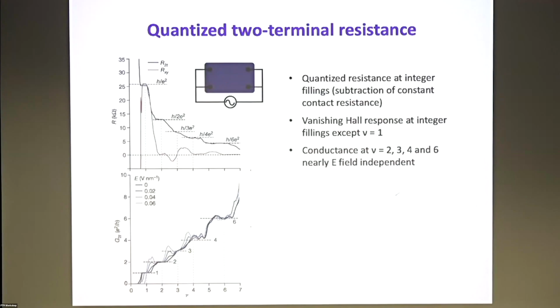What we do next is measure a two-terminal resistance as a function of the filling factor. This is the configuration. We short these two contacts and just measure the two-terminal resistance. We calibrate the contact resistance at very high doping and subtract off that one constant contact resistance. The blue curve is the two-terminal resistance after that subtraction. You can see these 1, 2, 3, 4, 6 states, and the one has a quantized Rxy, but all the other states have nearly 0 Rxy.